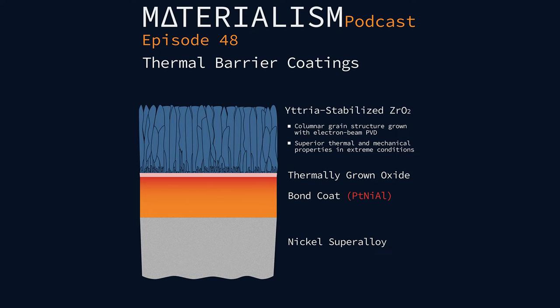The benefit here is the rate at which you can put it down. You can put down big, thick coatings. You can cover large areas, but it's not as high of a quality film. In fact, if you look at the microstructure of these two things, they look totally different. Imagine just dripping paint onto something. When it hardened, you're just going to get these flattened drops and kind of a lamellar structure is what they call it. Yeah, that's what they see.